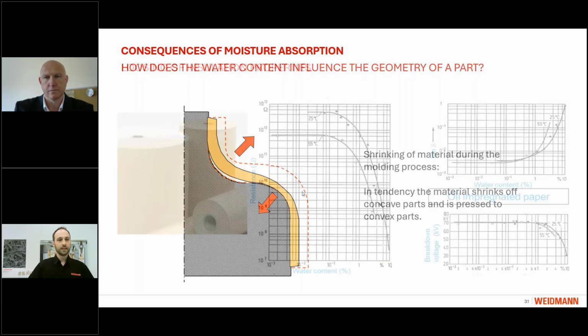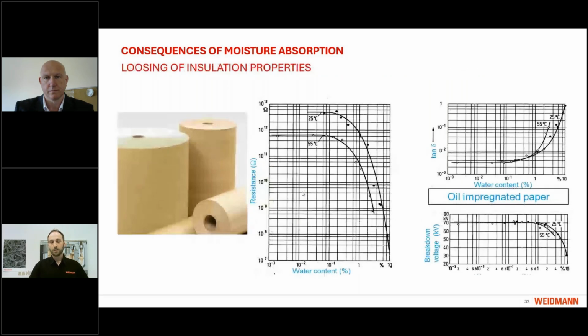Next, we go to the dielectric properties. Our material excels at really dry states. On the right-hand side, you can see oil-impregnated paper that was tested for its loss factor, tan delta, and breakdown voltage. We can really see that roughly at 1% water content, these values start to go out of the area that we want them in. So above 1% water content, our losses get higher, and above 1%, our breakdown strength is reduced. And again, this is of course temperature dependent.